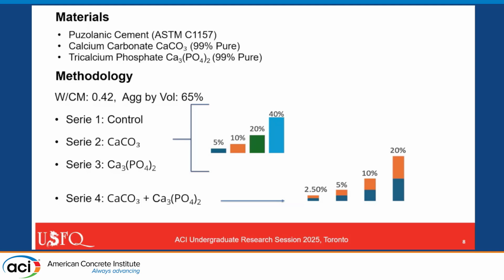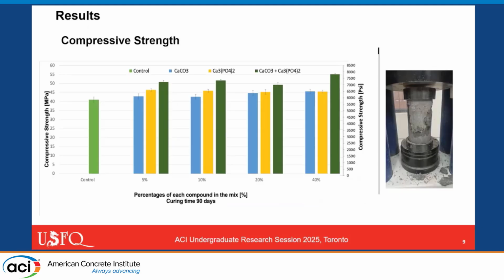For the methodology, we first created a control series with a water cement ratio of 0.42. Also, we had aggregate by volume of 65%. For the second series, we created a new sample with a partial weight replacement of cement with calcium carbonate. The third one is the same but with a partial replacement with tricalcium phosphate in different percentages by weight: 5, 10, 20, and 40. And the fourth series is the mix of both compounds, calcium carbonate and tricalcium phosphate, with the concrete.